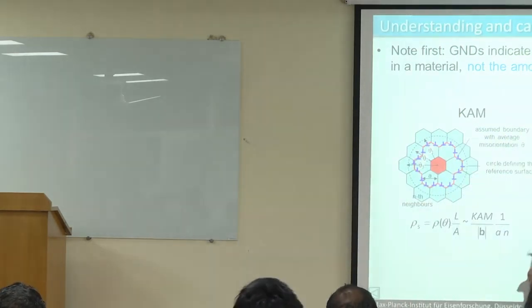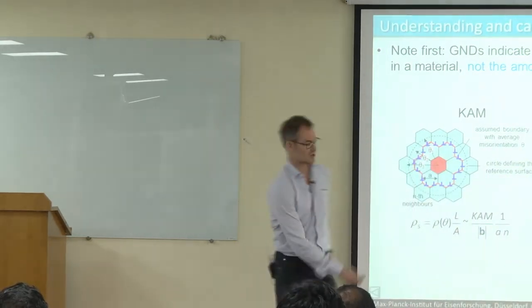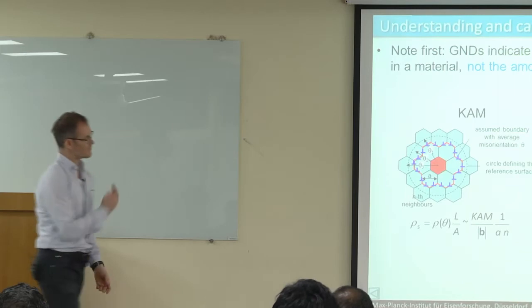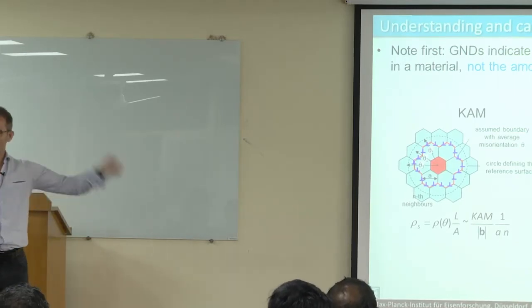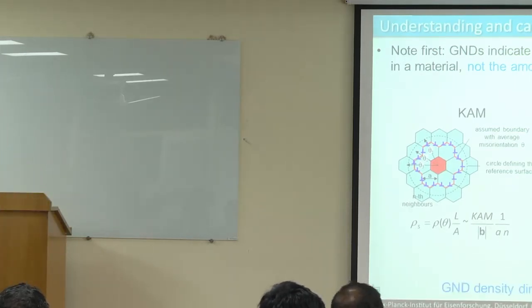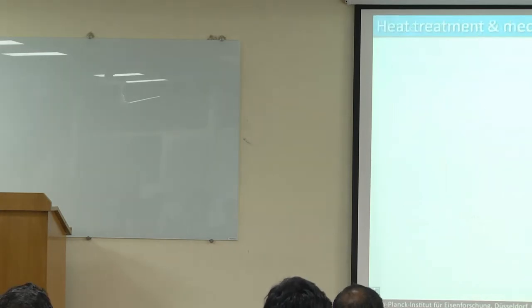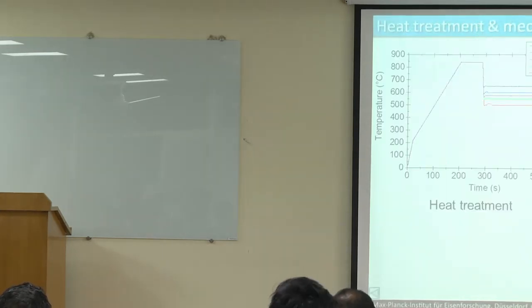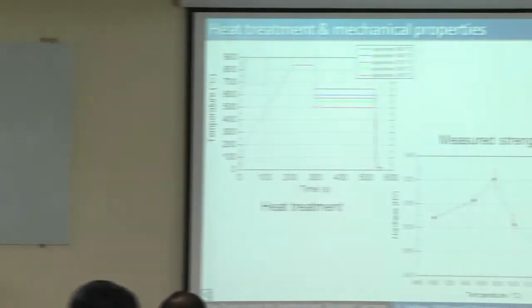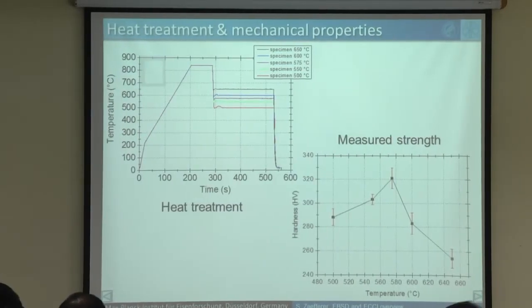This microstructure here has everything between 0 and 4 times 10 to the 15 per square meter dislocations. Okay, so now we have a nice measure of the amount of dislocations inside of a material. And we can use this now, for example, for the following beautiful thing. Now we come again to a materials example.